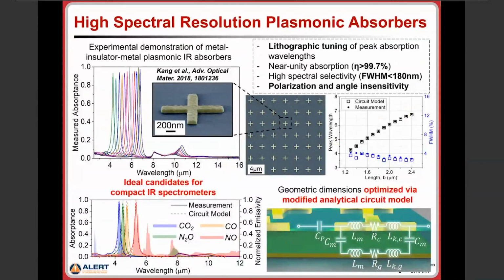That's what I'm showing here. It's possible to build these plasmonic structures to achieve extremely sharp absorption features. You can build lithographically, on the same chip, devices that can absorb very specific wavelengths of infrared radiation with very high spectral selectivity, and at the same time very high absorption efficiency. So close to unity absorption with a full width at half maximum that is less than a few percent or so. That's really an exciting feature.